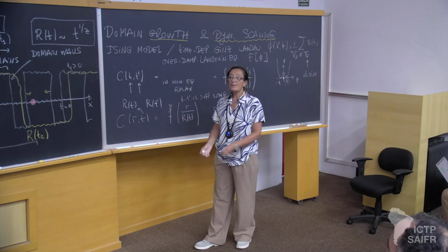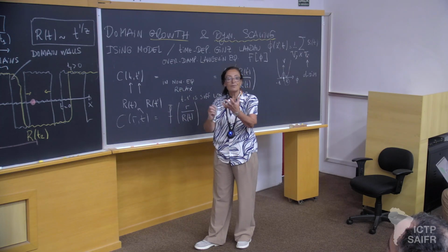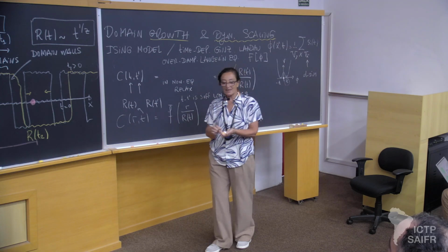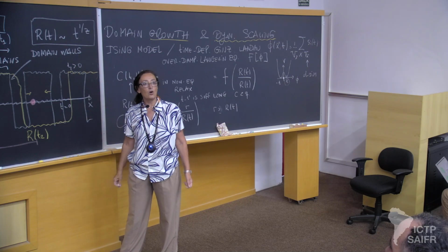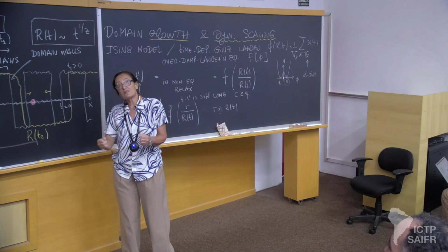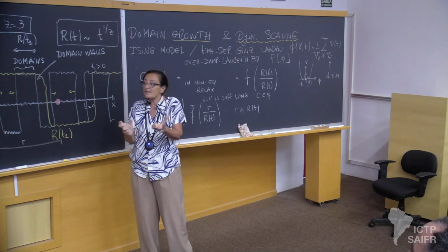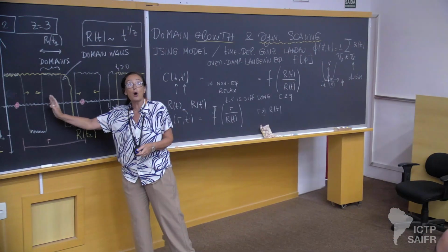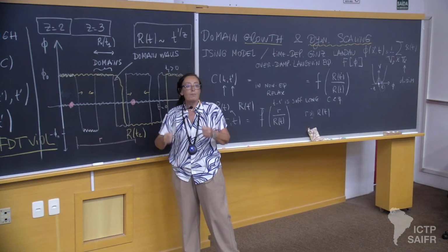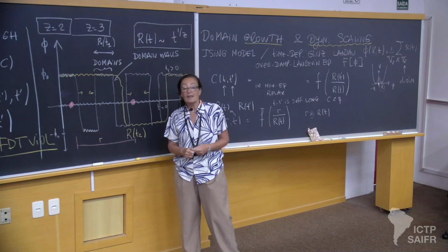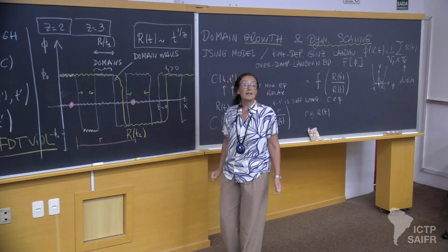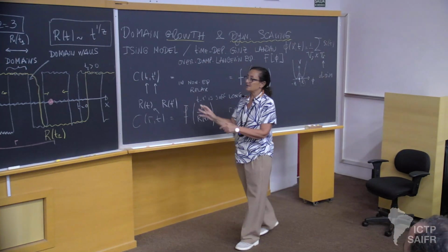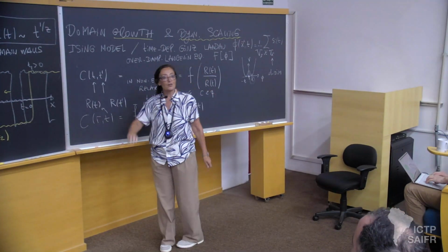And if you have randomness, so if you have quenched disorder, pinning centers, things like this, well, Ezequiel knows better. And then instead of being a power law, you will have logarithmic laws. So the dynamics becomes slower. The walls can move less because you pin them. You stop them with, I don't know, pinning centers, different kinds of things. So if you have randomness, you get slower growth than with the pure systems, Ising or phase separation problems.